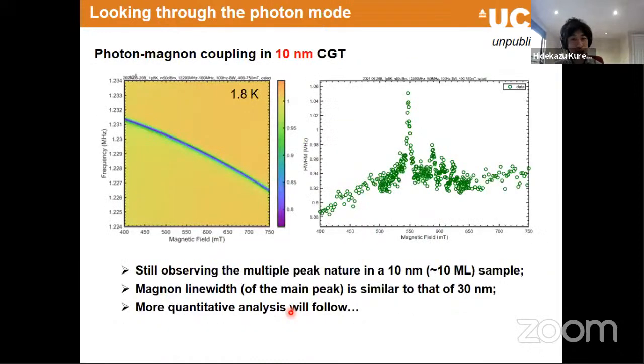I can quickly also show you that it is possible to measure the same thing in a 10 nanometer flake. By eye, it is very difficult to see any faint behavior, but the computer can still tell us that the line width sharply increases at this thickness regime. By improving that, we can go into a truly 2D regime to study the spin dynamics in the 2D van der Waals system.